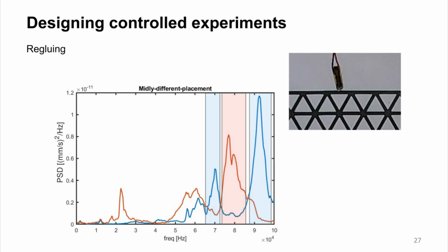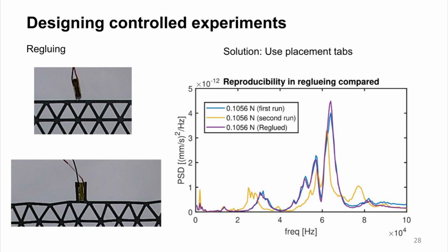Knowing this, here we can see that ungluing and regluing does have an effect, and that is presumably due to slight variations in placement of the piezo. Every time the glue cures, it hardens and puts the piezo in a slightly different orientation, or there might be mild differences in the location the piezo gets placed at. And as I can see, the peak features are different across both of the plots. To control this, I designed placement holders to make my placement of piezoelectrics more consistent, and the plots for these are better than the previous ones, and all the peak features are preserved across the 2 plots.